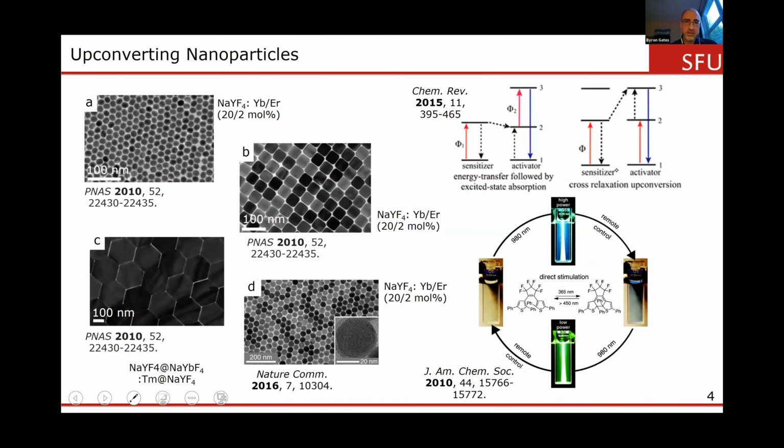And another area is looking at upconverting particles. This is an area that we also participated in collaboration with Professor Branda here at SFU. And so just as an example, upconverting particles are also optically interesting. And so depending on the intensity of a near-infrared laser, you can actually get two different emissions coming out. And that was utilized to be able to activate a ring opening effect and ring closing on a molecule that was dispersed in solution, but also then bound to the surface of those particles.